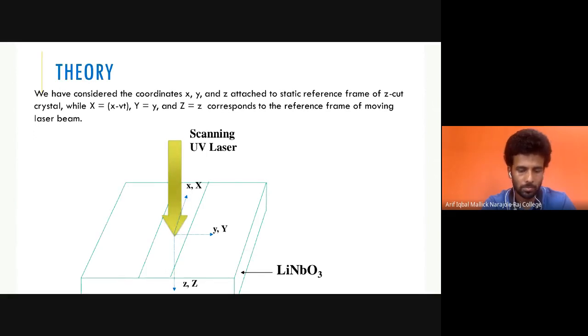We have considered two coordinate systems. One is fixed at the scanning laser beam, another is fixed to the lithium niobate. When lithium niobate is exposed to the UV laser, it absorbs heat and indiffusion takes place. The indiffusion increases the extraordinary refractive index in the exposed region, which guides the wave by total internal reflection. So it can be used as a waveguide.